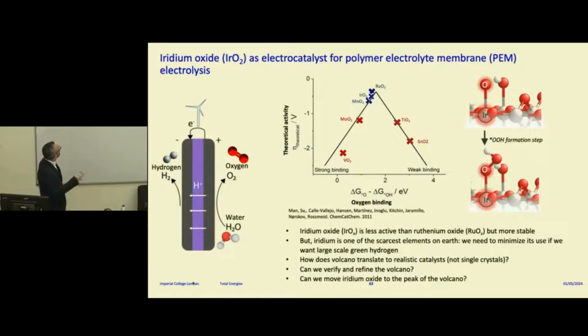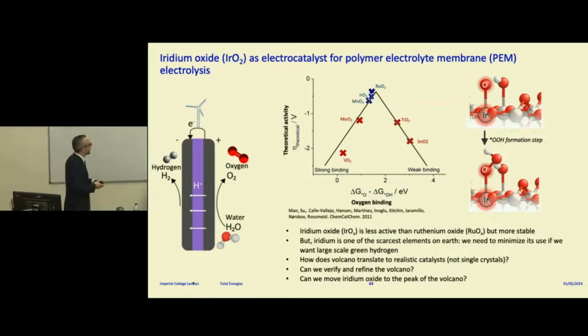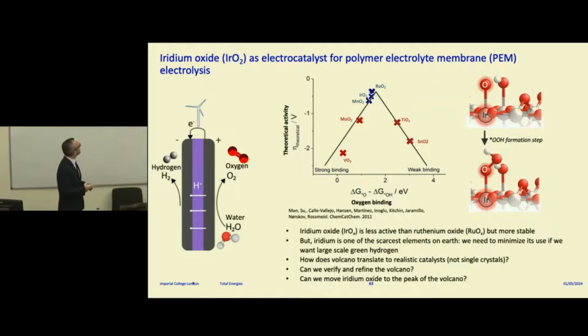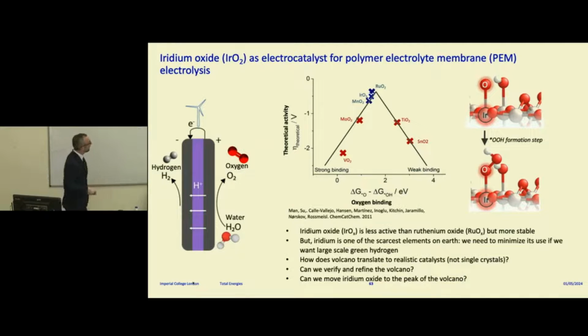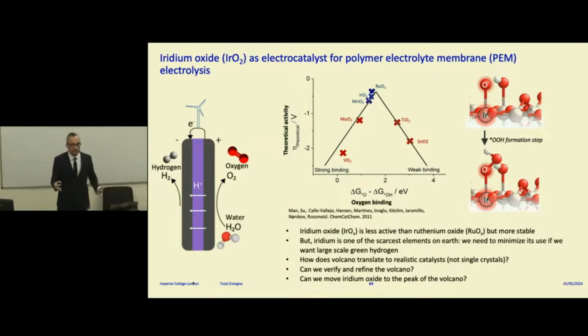So one thing we started being interested in: I already mentioned ruthenium oxide is the best catalyst for oxygen evolution. We studied that, and we did some really nice research with Reshma, MIT, and also the Technical University of Denmark. But the problem is it tends to corrode away. So as I mentioned earlier in my talk, iridium oxide is not quite the tip of the volcano, but works pretty well. The problem is iridium is one of the scarcest elements on Earth. So we need to minimize its use.